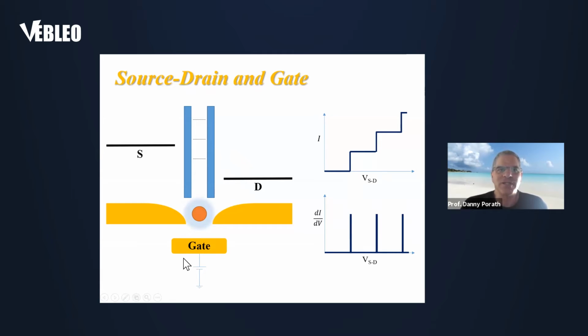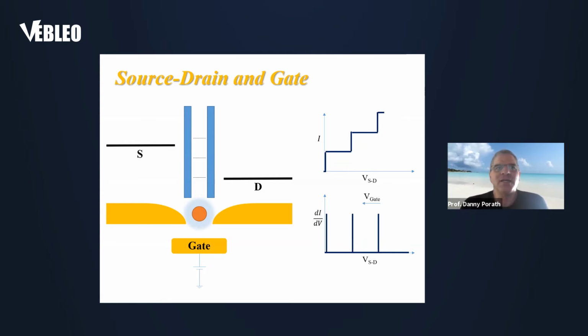But we can have a third electrode, which we call a gate, and this electrode is not electrically connected to any of the other two electrodes, the source and the drain. So there's no current flowing between the gate and these electrodes, but there is an electrical potential which is applied and affects the object between the electrodes. In this case, when there is some voltage difference, usually small, the application of the potential shifts the energy levels and shifts the position of these two curves, and it can provide us information on the density of states, and if there are charging effects, it will tell us how good the contact is between the object and the two other electrodes.